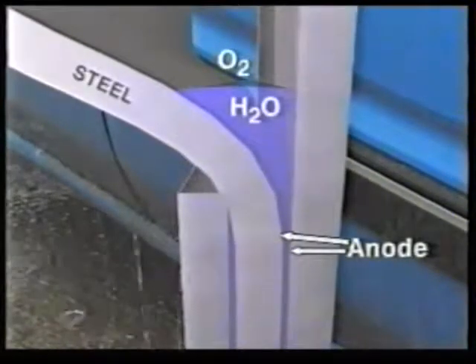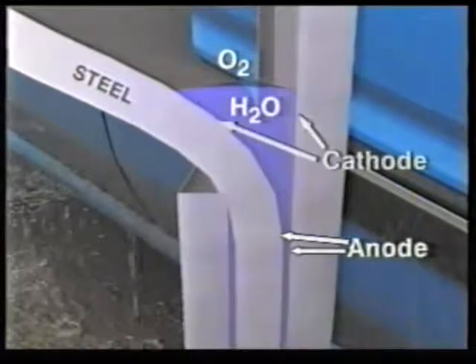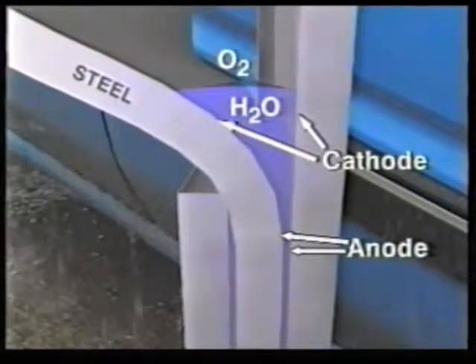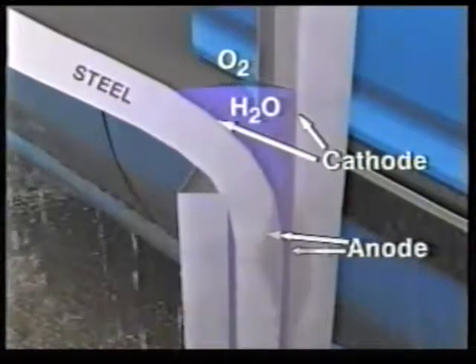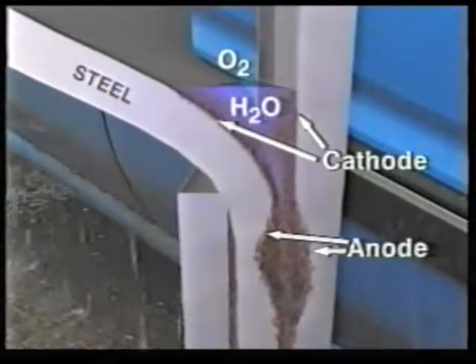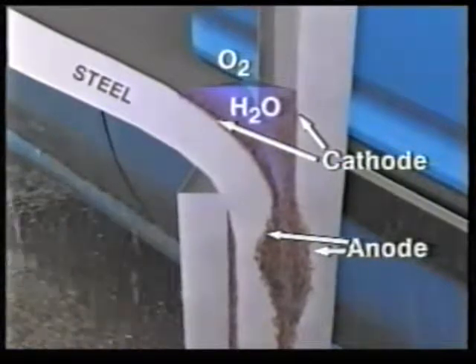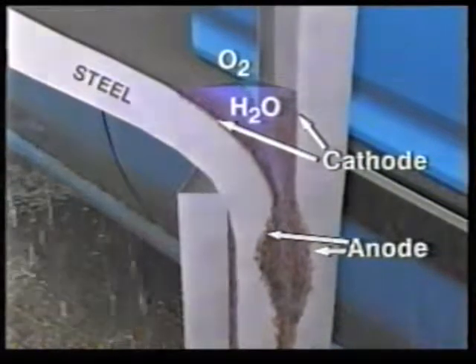Water can enter the door section through various routes, such as past the window rubbers, draining down to the bottom and getting drawn into the clinched seams, where corrosion occurs. This is the anodic centre within the crevice. And here is where the cathodic reactions take place, just outside the crevice. And here is the rust between the anode and the cathode, much accelerated by the presence of chloride ions in this confined environment, even though these concentrations may be small, as they are in rainwater, for example. This is crevice corrosion.